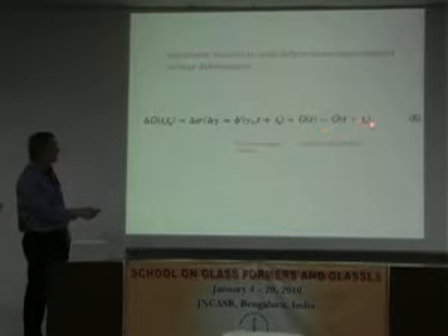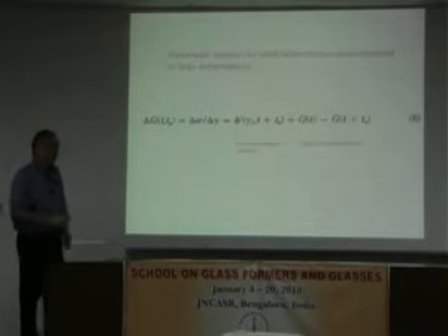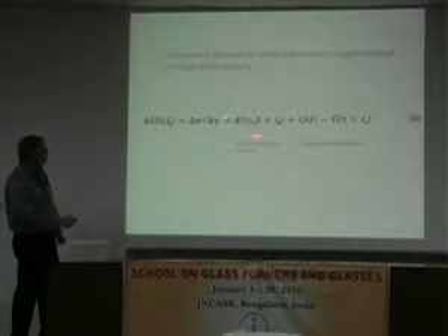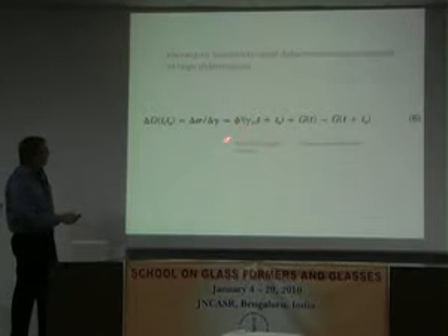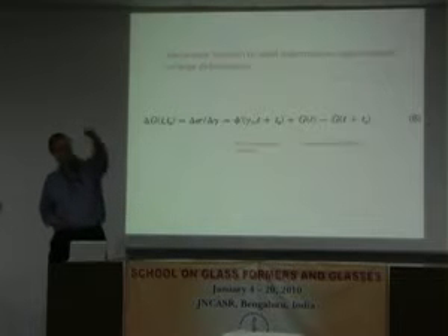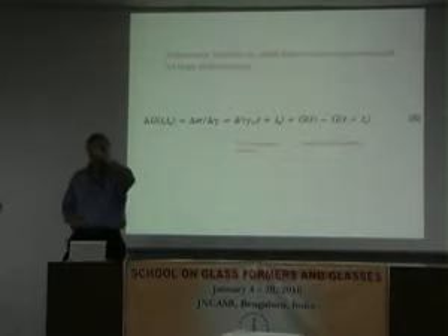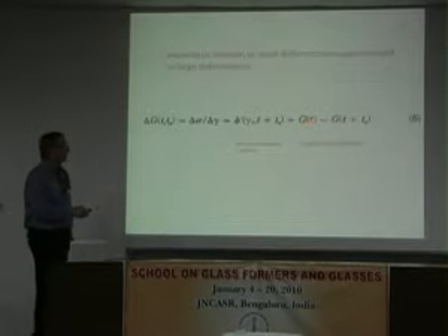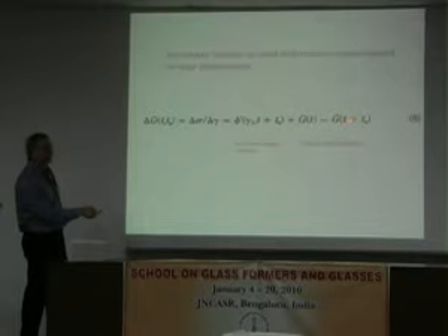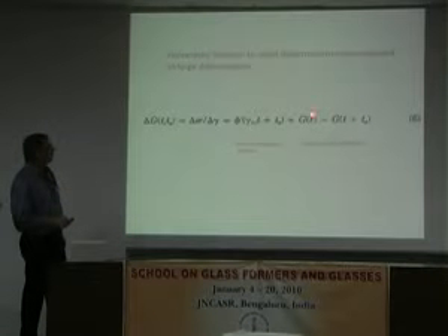So that's a long time. So it's a viscoelastic model, and this number is always smaller than this number. That's the first thing, so I'll always have a reduction of this from this. The other thing is this term is a tangent modulus. If I go up to 4% strain and my stress-strain curve looks like this, it's the tangent modulus. So that's also always smaller than this number. It's evaluated at the same argument here, so it's also always smaller than that. So in fact, what I'm always going to have is G at t minus something. That's always going to happen.